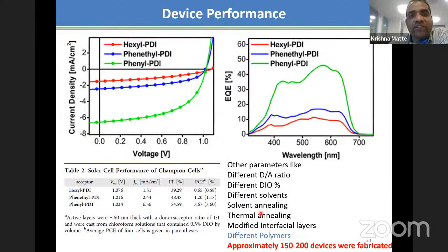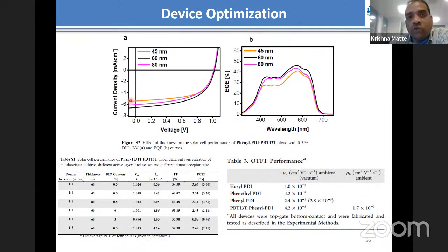Once you fabricate the solar cells among these three molecules which are synthesized, the phenyl PDI, the chain with the phenyl group, is performing better, and we wanted to know why this phenyl PDI is doing better. So for this phenyl PDI, we measured the device efficiency at different thicknesses, and we found that at a given optimum thickness of 60 nanometers, it works better. Even if you have low thickness, it is not good. If you have more thickness, it's not good,